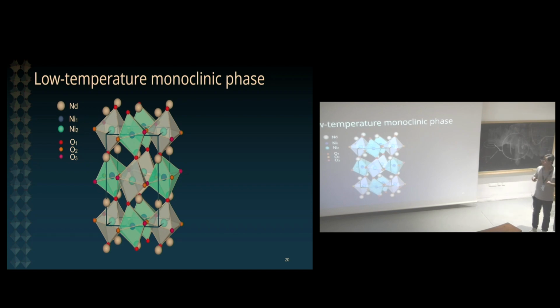So in the low temperature monoclinic phase, we have the nickel sites that are surrounded by either a small or a larger oxygen octahedron. So there is a breathing distortion that stabilizes a checkerboard pattern of small and large oxygen octahedra. So the local density of states here is strongly modified by this, and you have two inequivalent nickel sites.